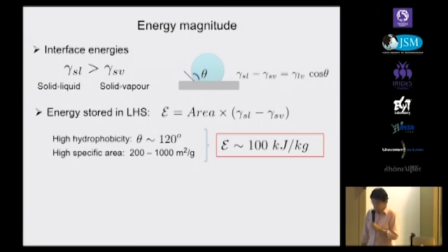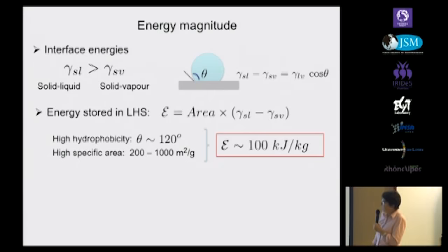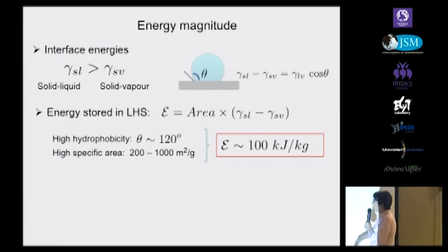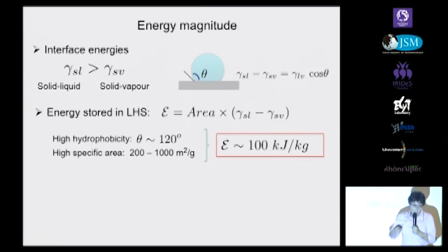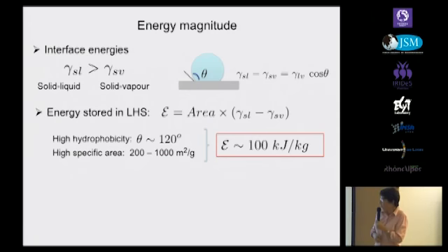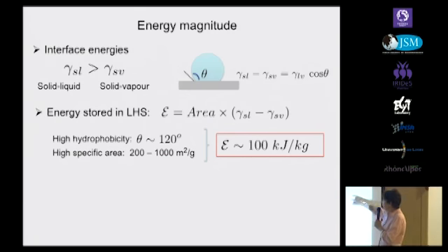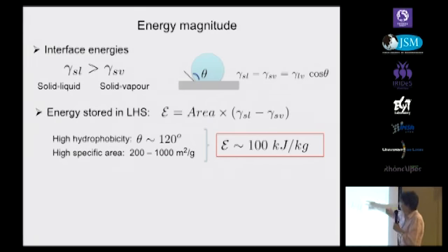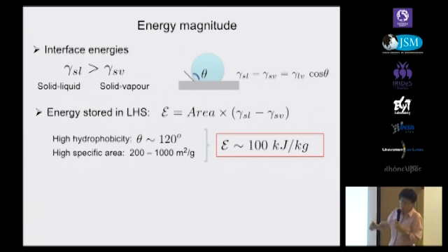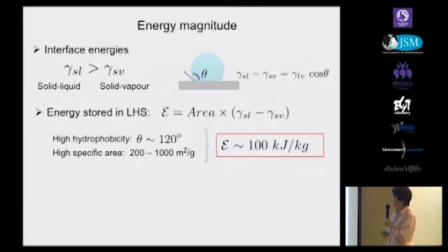The amount of energy involved in this transformation is the product of the area of the internal surface of the pore walls times the strength of hydrophobicity. The latter is the energy difference between the wetted surface and the dry surface.